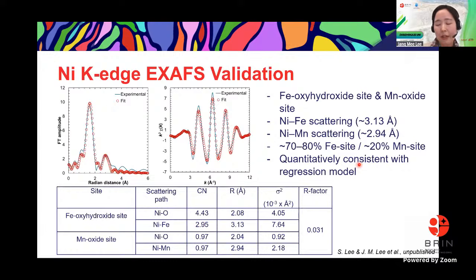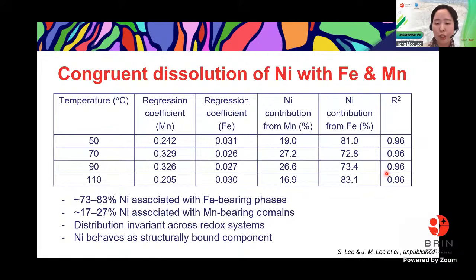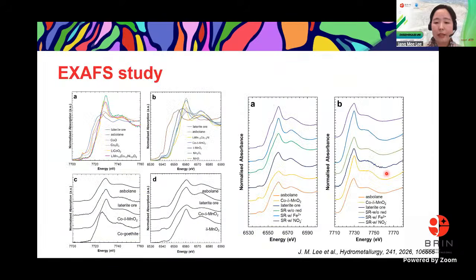Depending on the coordination factor, we are able to estimate the percentage of these scattering paths, nickel and iron, and nickel and manganese. So it was estimated that 70 to 80% of the nickel is from the iron side, the goethite crystal structure, and the remaining 20% is from the manganese side. So this result is quantitatively consistent with the regression model from the congruent dissolution. So yeah, this is another EXAFS study, an X-ray absorption spectroscopy study of the laterite ore.